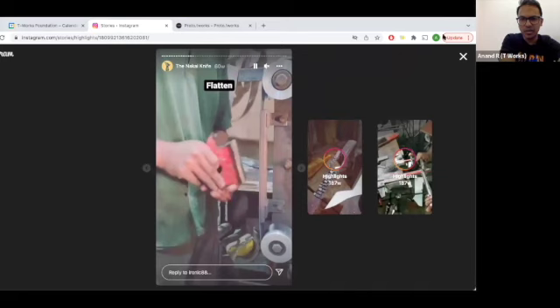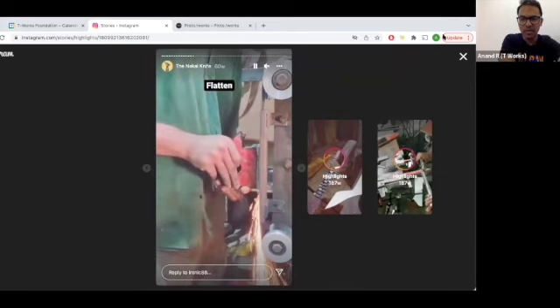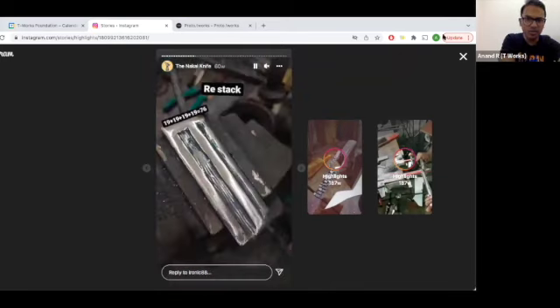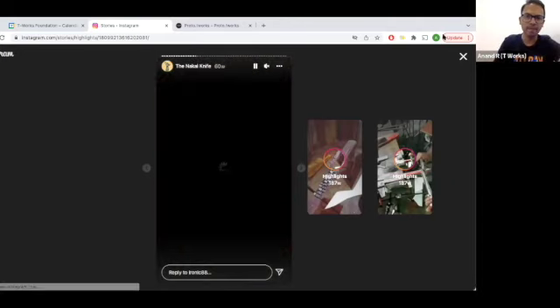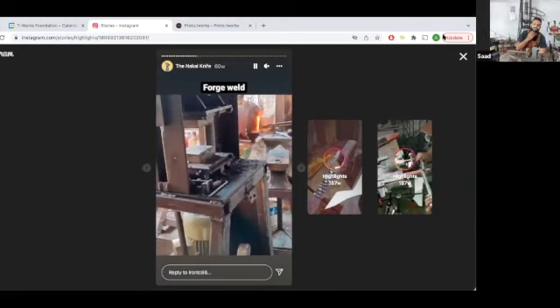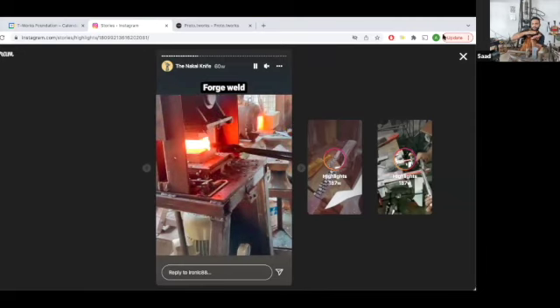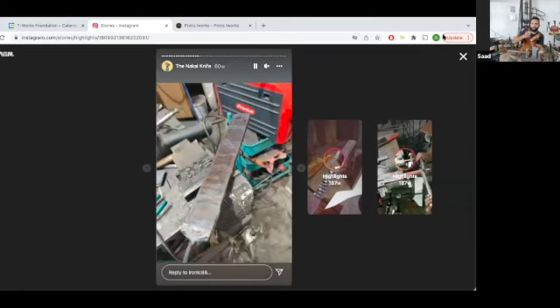And you started off with 19 layers, and I know so going up to 76 layers in this. That is insane. So you can go up to like 1,000 layers. I think the maximum I've done is 800 layers. Because you can start with as many layers as you'd like, but the more layers you have, the more chance of failure you have between the layers. So if I start with 10 layers, then there are 10 chances of it failing. Well, basically it's 10 into 10. It's about 100 chances of failure.